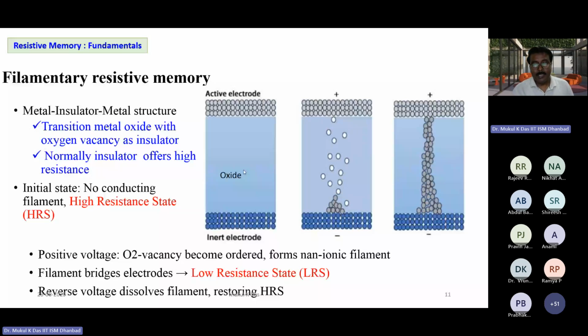Suppose it has two states, one is low resistance state called LRS, another is called high resistance state, HRS, when no voltage is there. These two states are there. But the problem is, can we guarantee these resistance values will change in a similar fashion if we repeatedly put the same voltage? That means suppose we are applying a voltage from 0 and increasing up to 4 volt. So its resistance suddenly reduces at 4 volt. Now we again retrace the voltage from 4 volt to 0 volt. So its resistance again becomes high. Now, second time, if we again increase the voltage from 0 to 4 volt, can we have the same formation of filament? No, that we cannot guarantee.